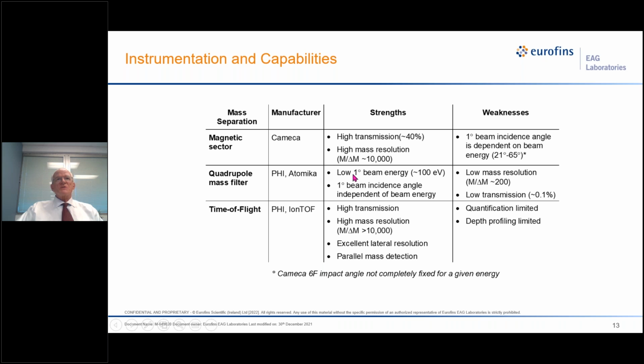The quadrupole mass filter has low primary beam energies, can go as low as 100 volts. And the primary beam angle is independent of the beam energy, but it has low mass resolution. We have no way of resolving any mass interferences, and it has, I won't say low transmission, but certainly lower than a magnetic sector. Time of flight has high transmission, high mass resolution, excellent lateral resolution, parallel mass detection.